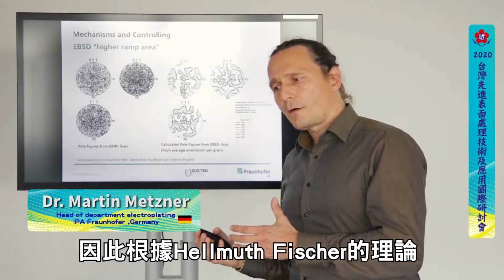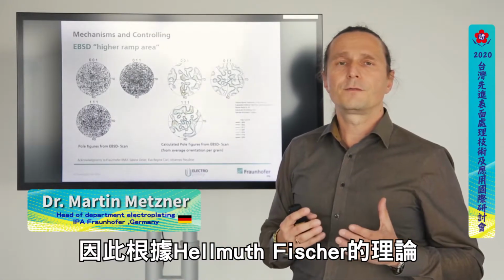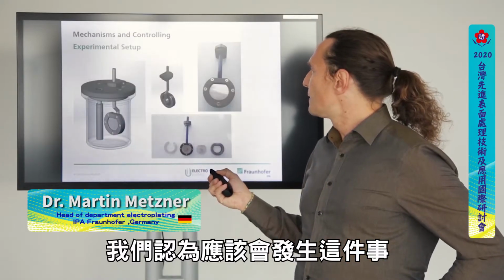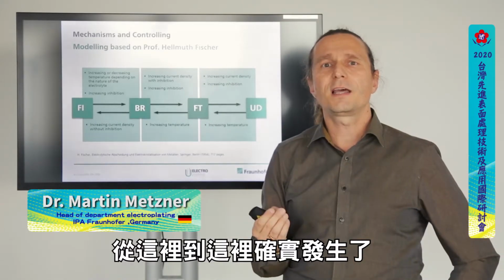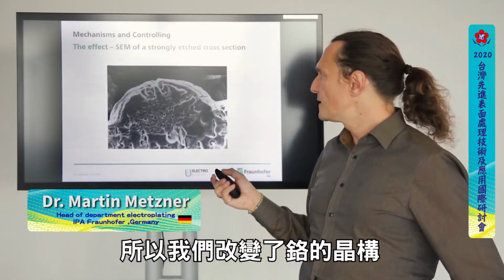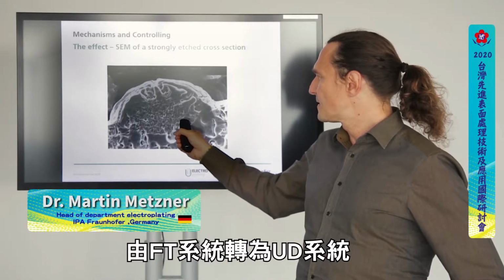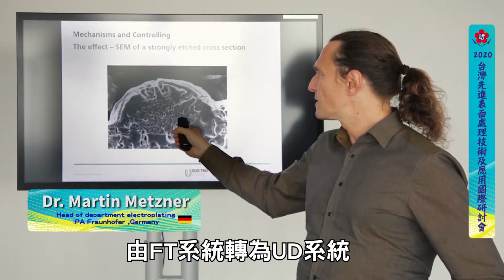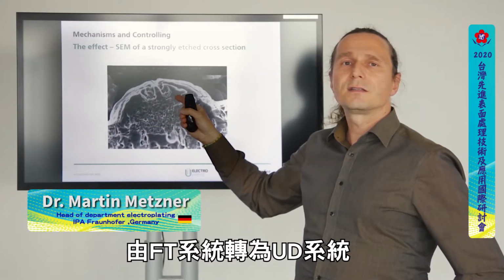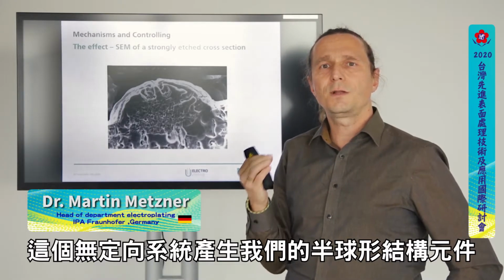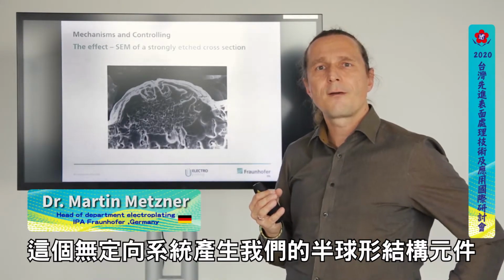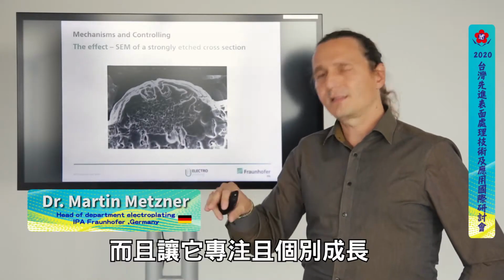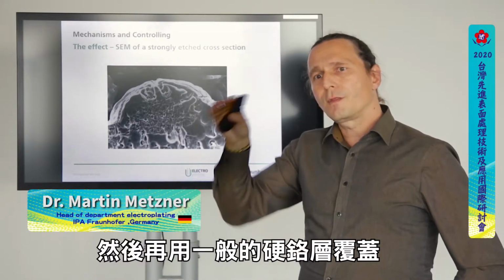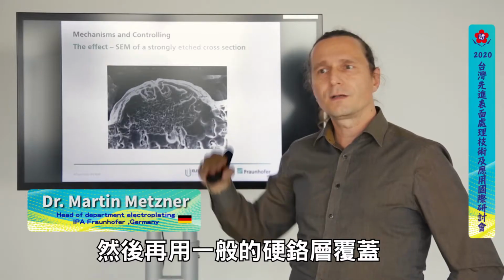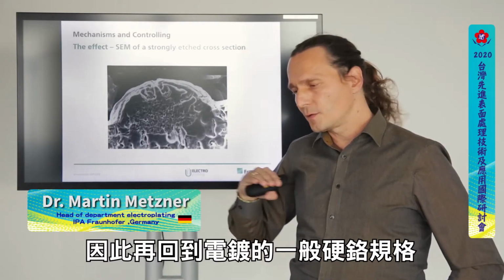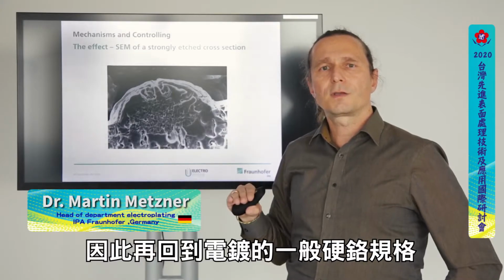So what we thought from theory from Hellmuth Fischer should happen in this thing, coming from here to here, it really happens. So we change the crystalline structure on the chromium from the field-oriented system into the unoriented system, and this unoriented system is building up our hemispheric structure elements and is growing them specifically and separated, and then we cover the whole thing again with a normal hard chromium layer. So we go down again to the normal hard chromium specifications of our plating.